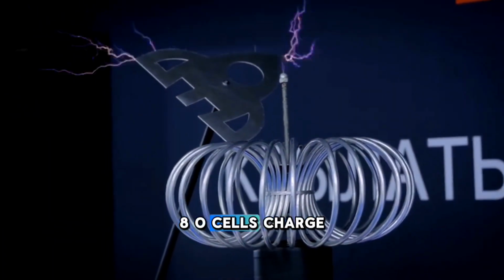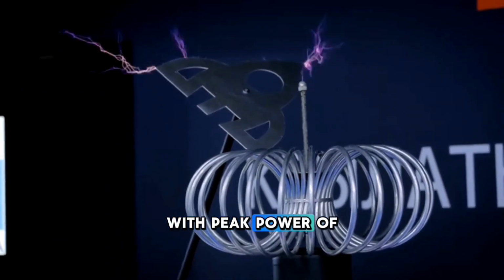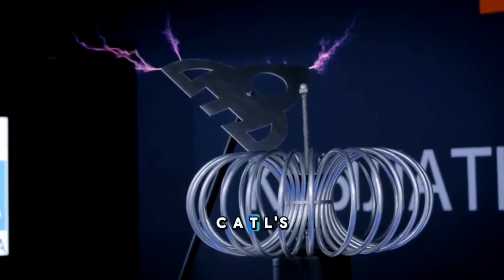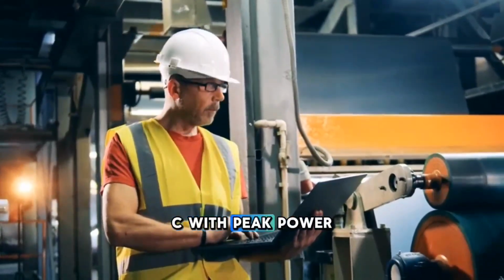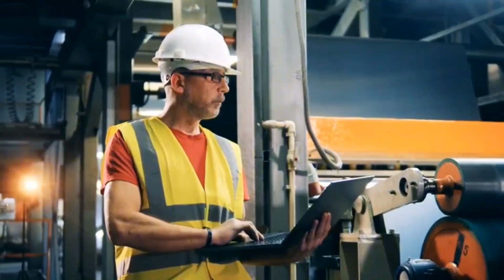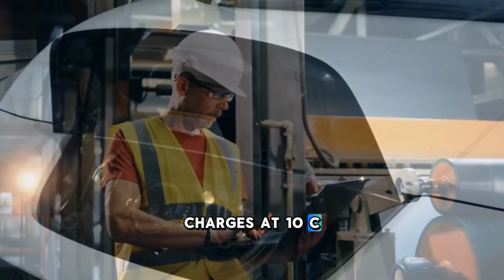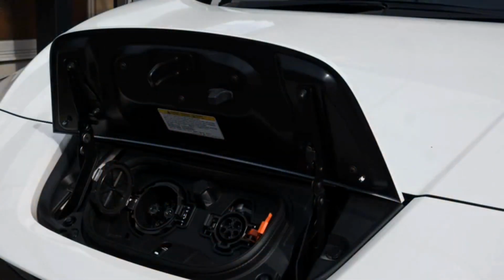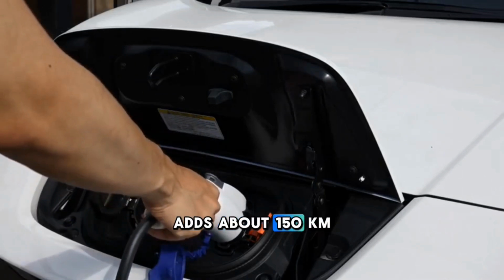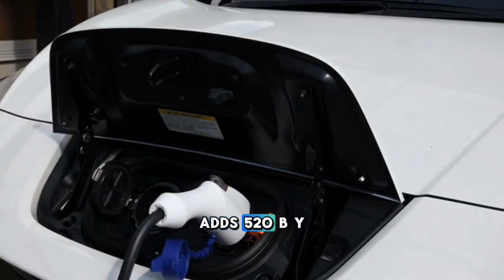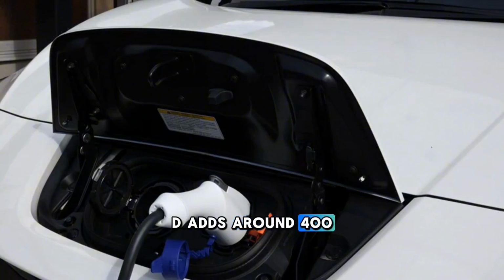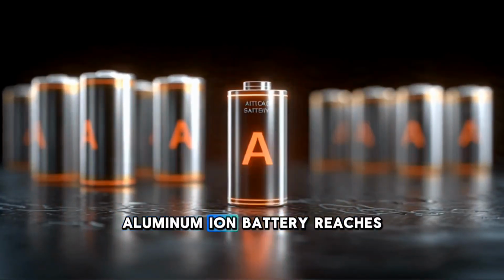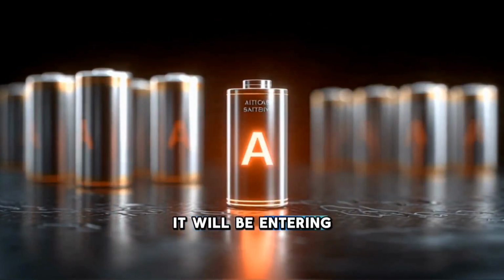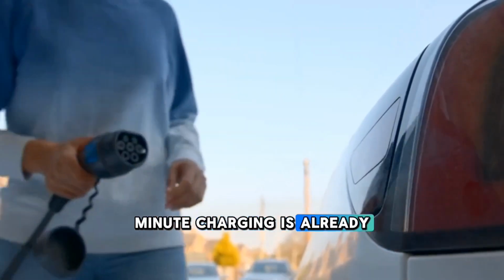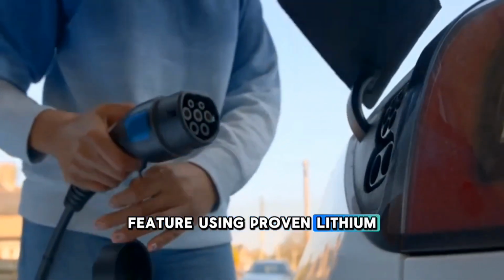Let me put this in perspective. Tesla's 4680 cells charge at around 3C with peak power of 250 kilowatts. CATL's Shenxing charges at 12C with peak power of 1300 kilowatts. BYD's Blade charges at 10C with peak power of 1000 kilowatts. In 5 minutes, Tesla adds about 150 kilometers, CATL adds 520, BYD adds around 400. By the time any aluminum-ion battery reaches the market, it will be entering a space where 5 to 10-minute charging is already an established feature using proven lithium chemistries.